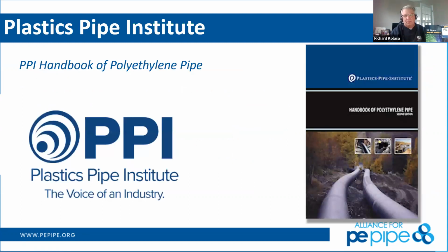And I just showed the report. There was really nothing that they detected. There were 2 items they detected below 0.1 parts per million, which is just above a detection level, but well within the health factors that we don't have to be concerned about.